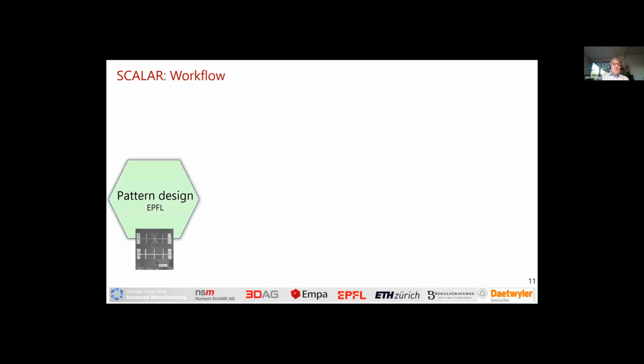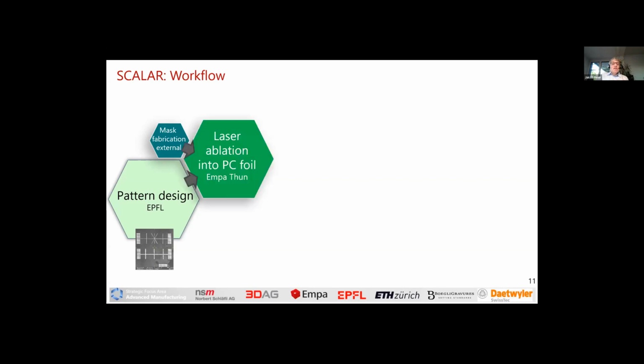Now, what we do in Scalar, we actually do not engrave the cylinder directly, but we laser pattern a polycarbonate foil. We do this on a model pattern where we can implement a lot of different features to really understand where the optimum is. So in this pattern, we actually have something like 170 different configurations of cell shape, aspect ratios, and periodicity.